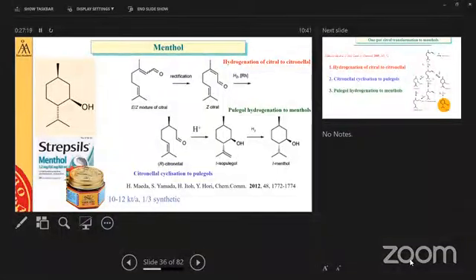So we start with citral, which is an unsaturated aldehyde, and you see here the conjugation between the carbonyl group, the double bond, and then there is an isolated double bond in the molecule. So what we do first, from citral, then we make so-called citronellal by hydrogenation of this double bond. It can be done over rhodium, ruthenium, or nickel. The first is hydrogenation of this unsaturated aldehyde, the double bond here. So we need to have a metal function here. The second step is cyclization of citronellal to isopulegol, and that requires some acid sites. Then we form isopulegol, and then the next step is hydrogenation of this double bond here over the metal.